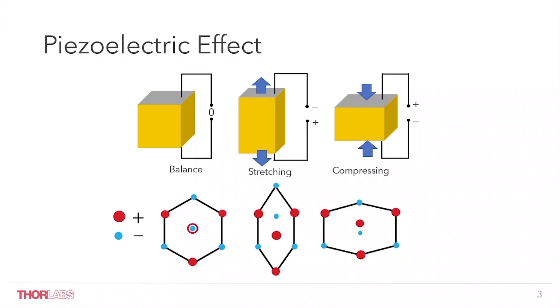When the piezoelectric crystal has a balanced status, the positive ion centers and negative ion centers are in the same position. When the crystal is exposed to internal stretching or compression, the crystal will deform.